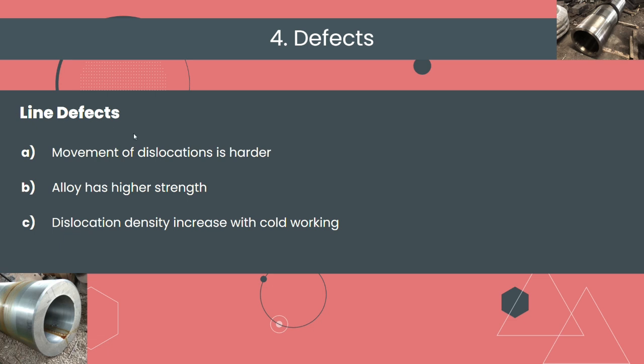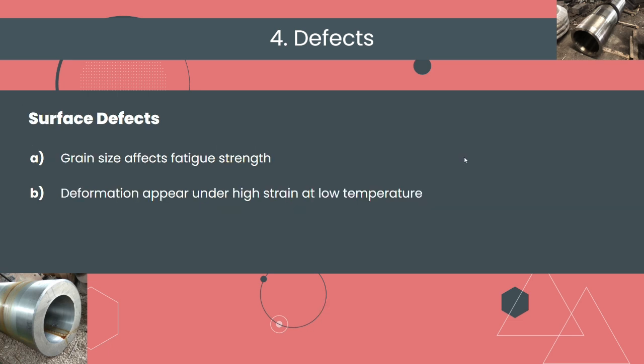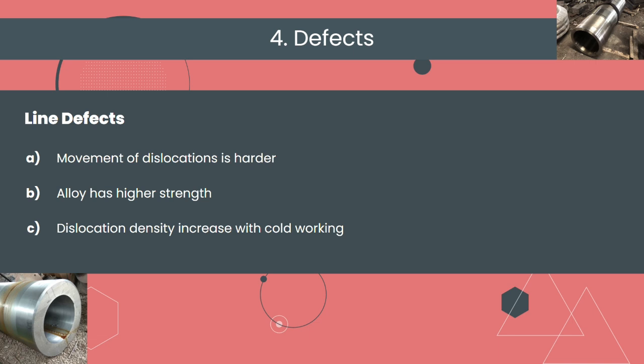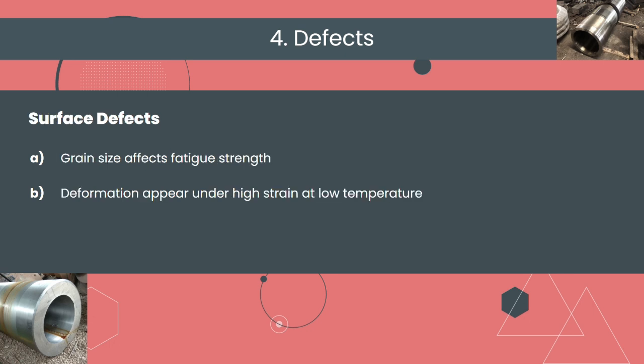So then the line defects, so movement of dislocations, they are harder. Then the alloy has a higher strength, and dislocation density increases with cold work. And lastly, the surface defects that I would like to talk about is that the grain size does affect the fatigue, and the deformation appears under high strain at low temperature. So as we saw before, dislocation density increased with cold working, and now here, low temperature, that tells me maybe we shouldn't work with this material at low temperature.